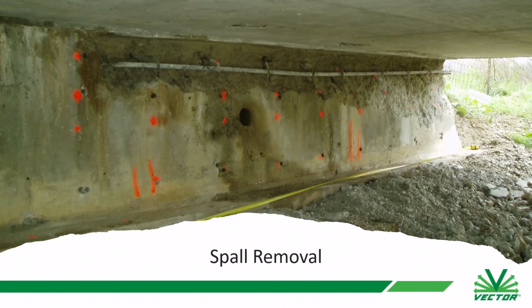The first step here is to do your removal of spalls or delamination. So you have to remove your unsound concrete. But because you're providing a cathodic protection system in conjunction with the repair, a lot of times they're just removing unsound concrete. They're not aggressively extending the areas of repairs or what have you. Removing all the chloride contaminated concrete, you can leave that in place.